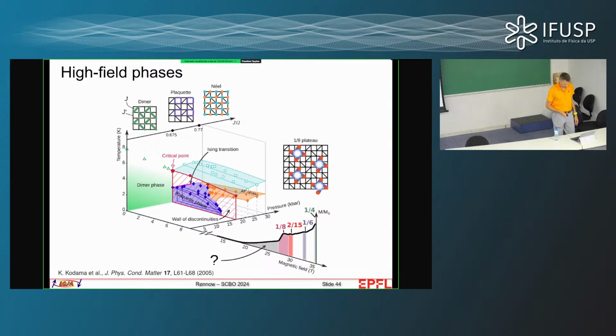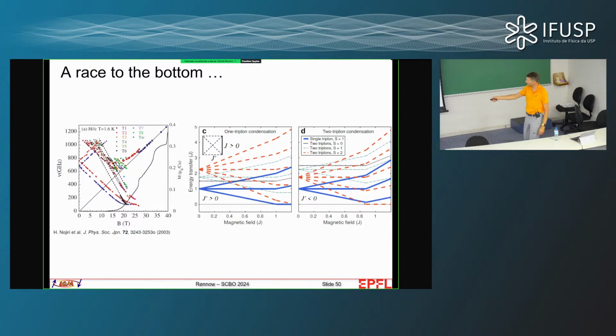And so we looked into that, and what happens is that as you apply magnetic field, you have the triplet excitation coming down, and you would expect that to hit the ground state here, and then you would have a Bose condensation of triplets into the ground state. But you can also have two triplets. If they go close together, they can form a bound state. So now I have a two-triplet state with spin 2, and the magnetic field will decrease the energy of that one twice as fast. And now it becomes a bit difficult to see, amongst other things because of this Dzyaloshinskii-Moriya interaction, which of these actually hits zero first. So which ones are condensing? Are we creating a Bose condensate of triplets or of two-triplet bound states?